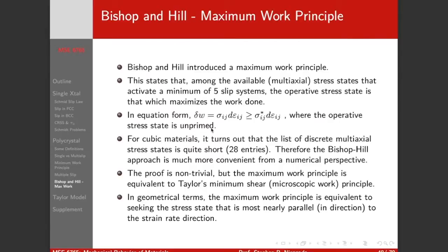Previously, we said we're going to choose the slip systems by minimizing the work done. In terms of the minimum work, we have a prescribed deformation — we want our grain to deform in a certain way. The minimum work principle says I want to do the least amount I have to do to get there, the least amount of shear necessary. I don't want to do any extra slip. Moving dislocations takes energy, so I want to do the minimum possible.